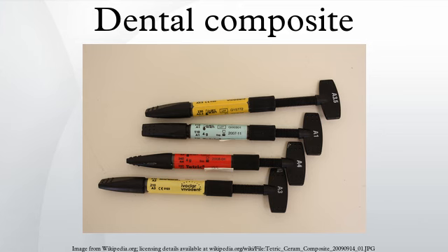It is challenging to harden all of the composite, since the light often does not penetrate more than 2–3 mm into the composite. If too thick an amount of composite is placed in the tooth, the composite will remain partially soft, and this soft unpolymerized composite could ultimately lead to leaching of free monomers with potential toxicity and/or leakage of the bonded joint leading to recurring dental pathology.